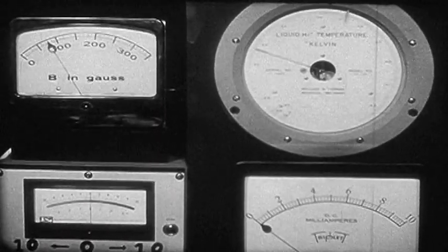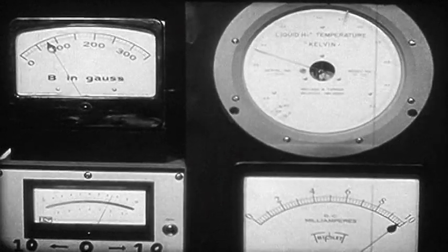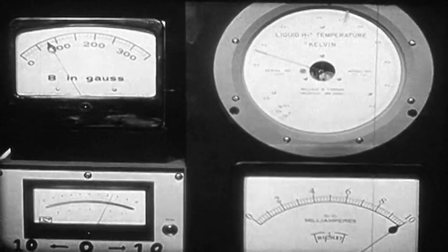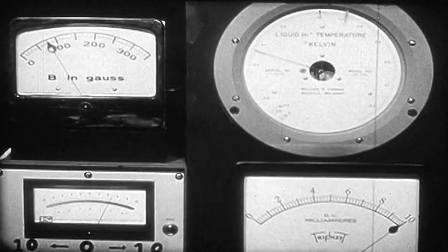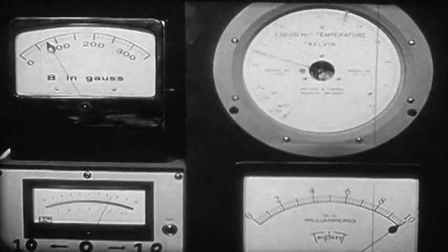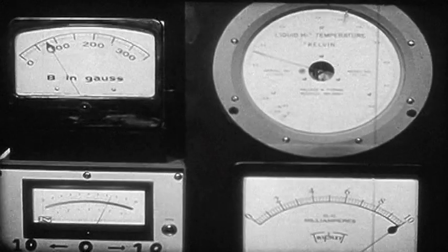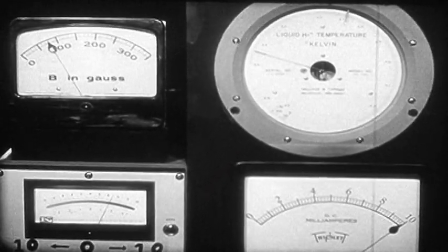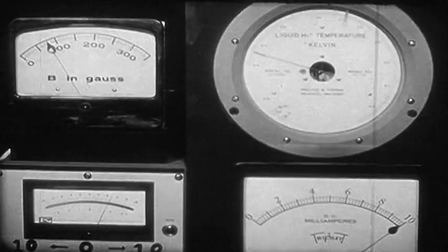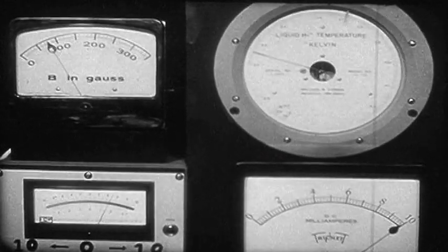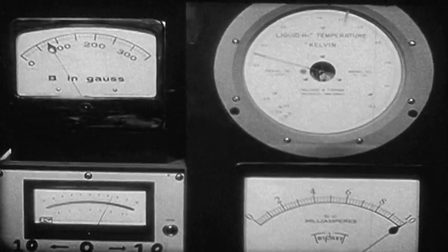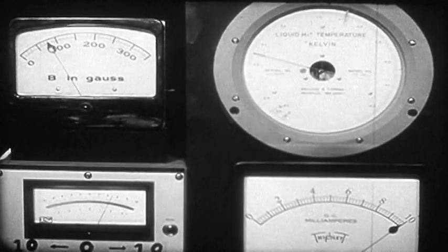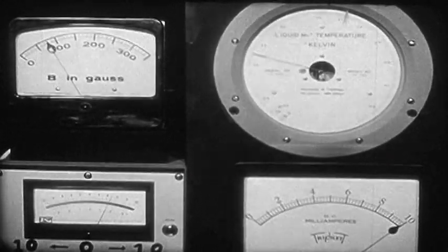The same current which we used in the previous experiment is again flowing through the wire, and it registers the same IR drop on the microvoltmeter. Clearly, the tin sample is in the normal state, but notice that its temperature is already much lower than 3.71 degrees Kelvin. This was marked off in the previous experiment as our value for the transition temperature of tin in the absence of an external magnetic field.